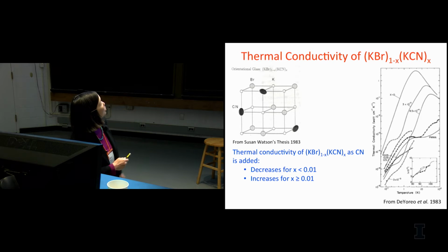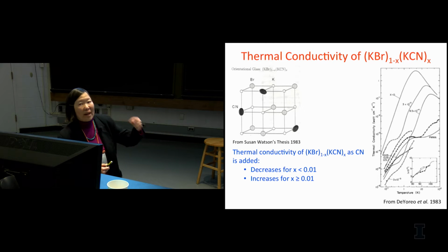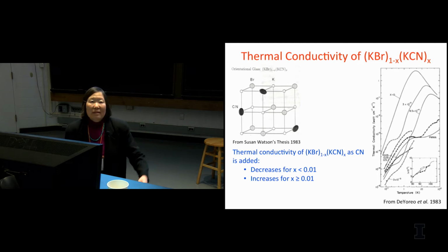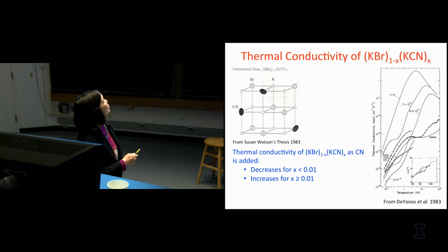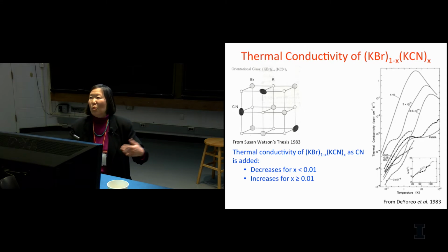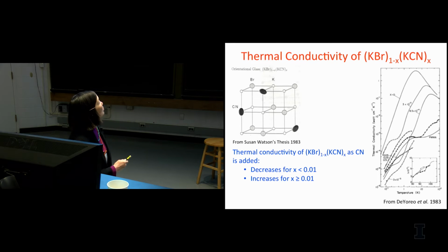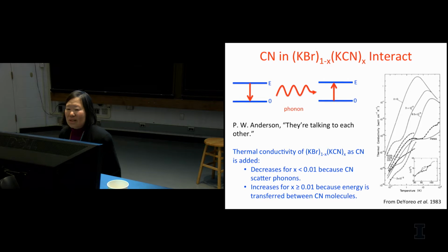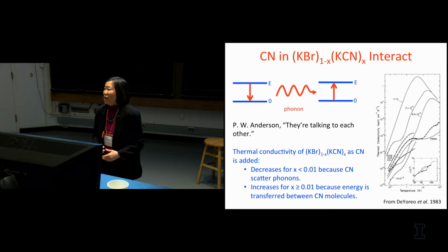So what Bobby Pohl's group did is they measured the thermal conductivity versus temperature as a function of what happens as you add in these cyanides. And they found that as you add in the cyanides, the thermal conductivity drops initially because you've got more stuff to scatter the phonons, so less thermal conductivity. But at some point, around 1% cyanide, the thermal conductivity started to rise again. And I showed this to Phil Anderson. He said, they're talking to each other.